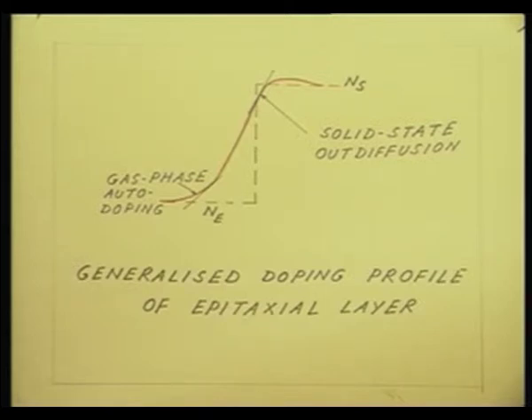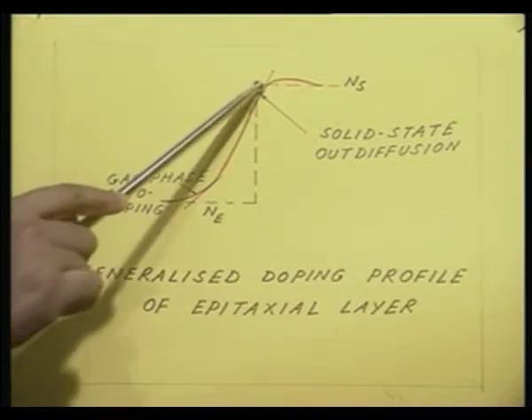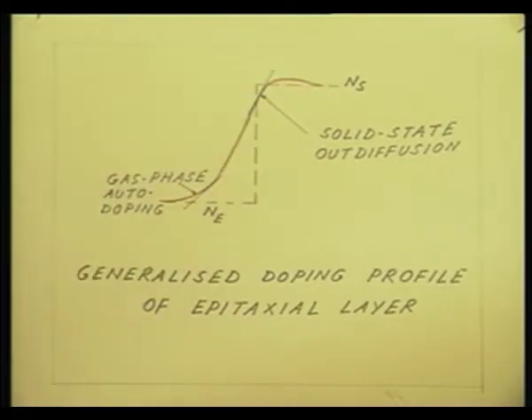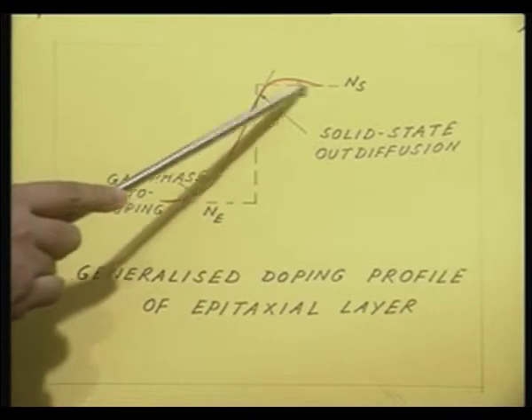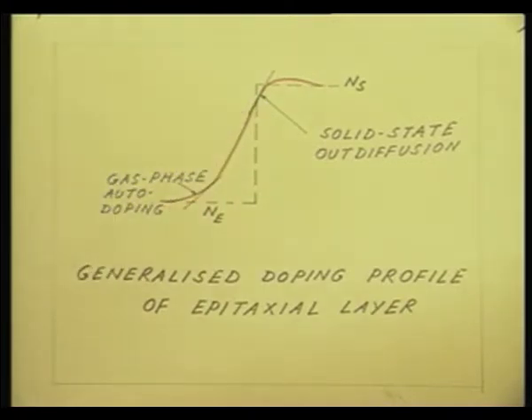The situation is analogous to bipolar junction transistor fabrication, where you have an N plus layer diffused in the P region. So, this is actually signifying the N plus layer diffused with high doping concentration, and on top of that you are trying to grow an epitaxial region of moderate doping concentration. So, ideally speaking, this should be my abrupt junction between the epitaxial and the bulk region, the abrupt transition. In practice, however, it is never like that, and what you have is this red curve. And this is a generalized doping profile.